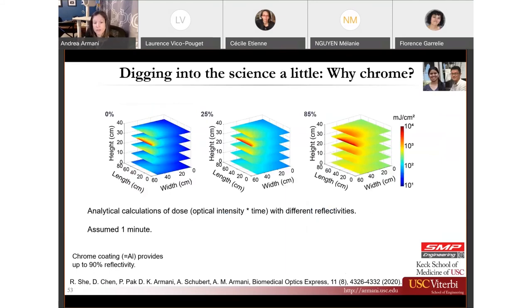We did a little bit of modeling to get rough calculations on how long we should put a sample in there to get that dose intensity. Assuming either a 25% or an 85% reflectivity, because remember, aluminum theoretically has 90% reflectivity, with a 1 minute exposure time we should have over 100 millijoules per centimeter squared throughout the box. Obviously, exposure is nonlinear throughout the box, but even in the farthest corner, it's still over 100.